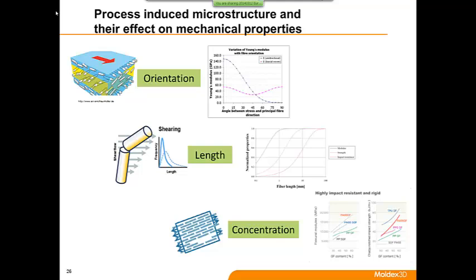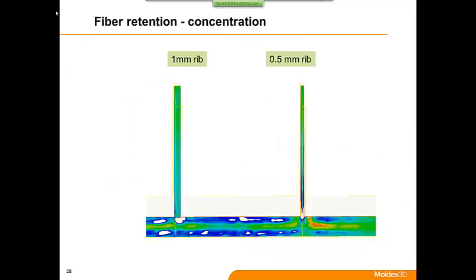So we can also do a concentration analysis. For example, in this case, we show two different kinds of product ribs. You have a 1 millimeter rib and a 0.5 millimeter rib. In this case, the red color denotes a high concentration of the fiber. So you can see in the 1 millimeter rib, the fiber can enter the rib without too much problem. It's really homogeneous. But if you check the 0.5 millimeter rib, because the rib thickness is close to the fiber length, a lot of fiber will get stuck at that entrance.